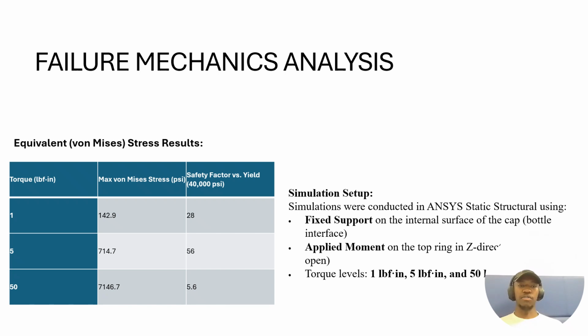When I applied the 5 pound force inch torque, it yielded about a 700 psi max stress, and that was about a 56 safety factor. And I increased that tenfold, so I applied a 50 pound force inch torque, and that yielded about 7,000 psi, which gave me a safety factor of 5.6. So I used this data for failure mechanics to predict the torque at which the yielding and potential failure could occur.